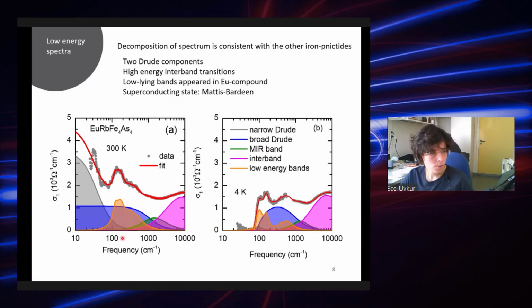So basically, you have these two Drude components. One is narrow and the other one is rather broad. In the iron pnictide community, it's always known that this is the case when you decompose optical conductivity spectra: you always come across broad and narrow Drude components. Then the high energy interband transitions are there. And for the europium case, which was different from the calcium-potassium case, there are some low-lying bands, which I showed here with the orange color.